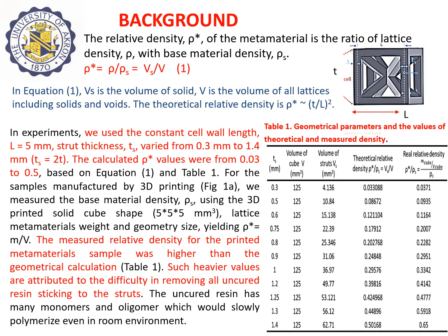The relative density rho star of the metamaterial is the ratio of lattice density rho with the base material density rho s, and the relations of the rho star to the volume and density values are shown in equation 1. We use constant cell wall length L equal to 5 mm. Strut thickness T sub s varied from 0.3 to 1.4 mm, and the calculated rho star values were from 0.03 to 0.5.